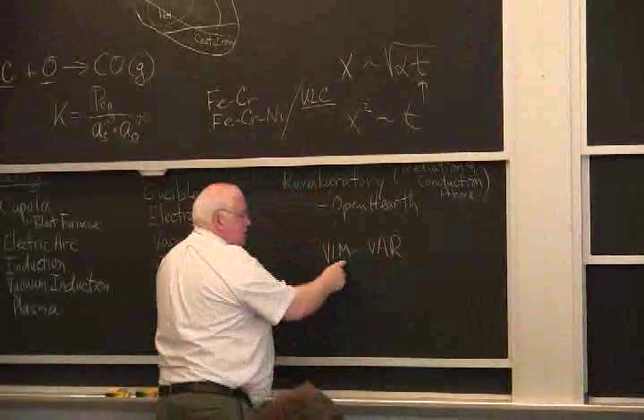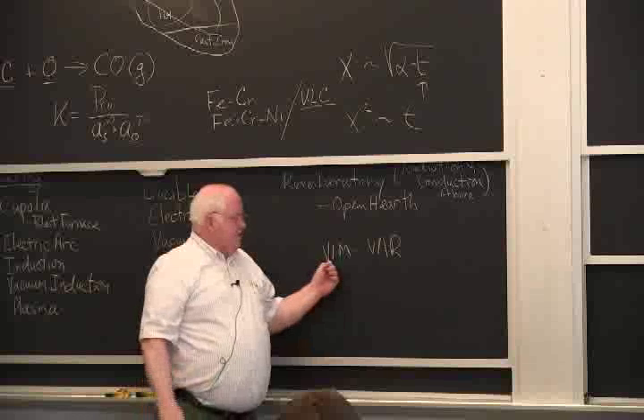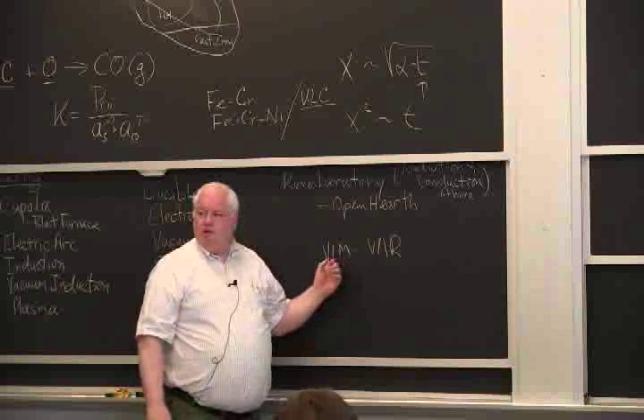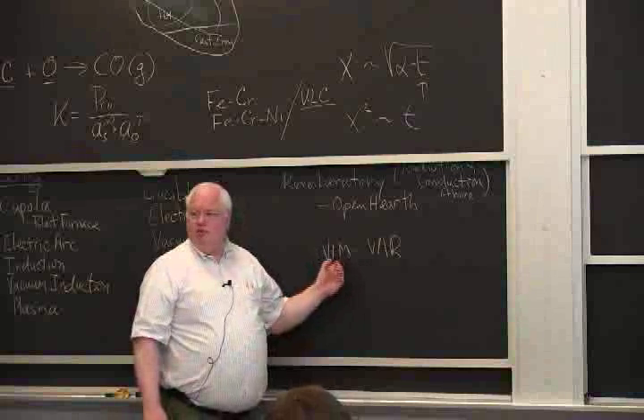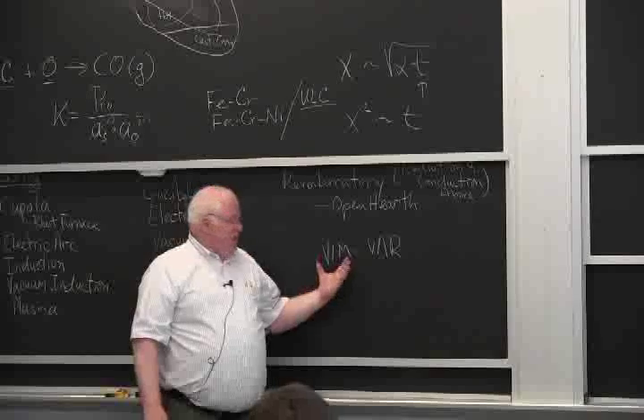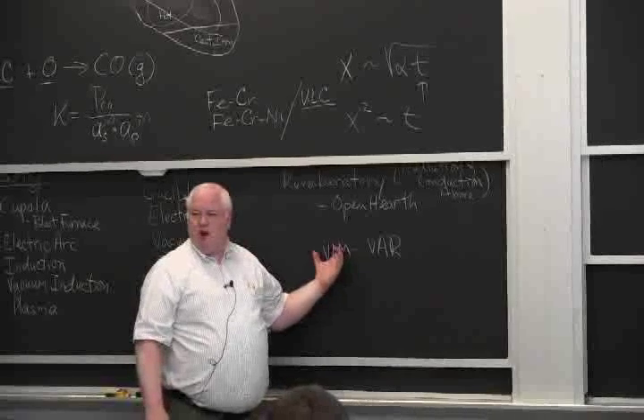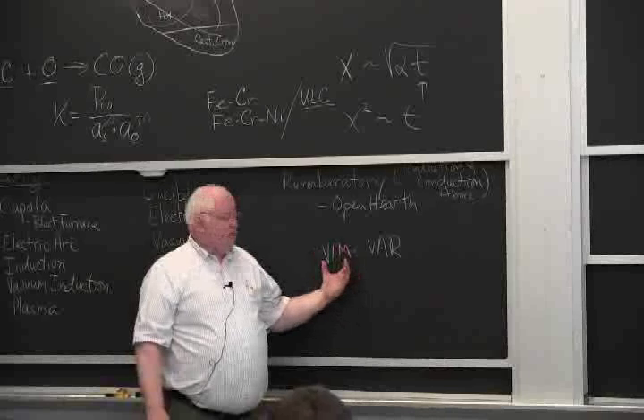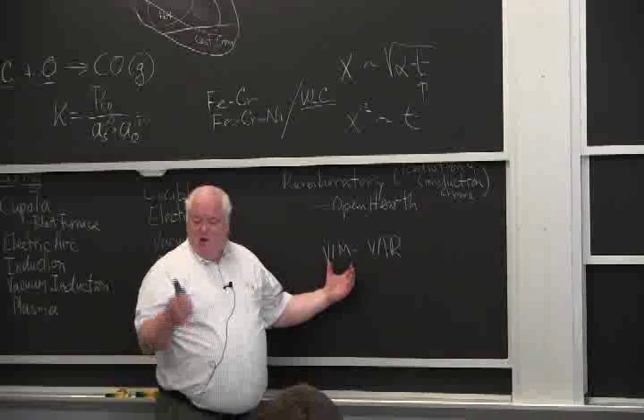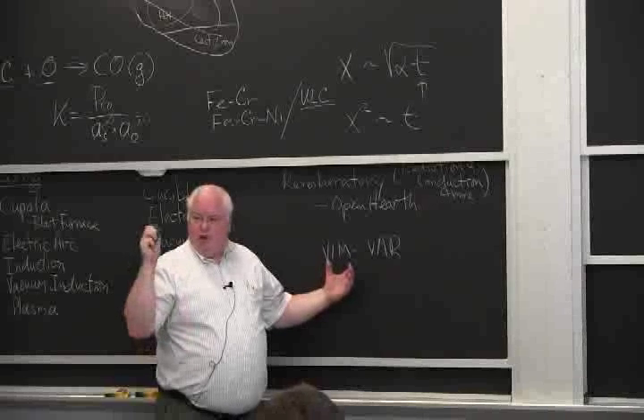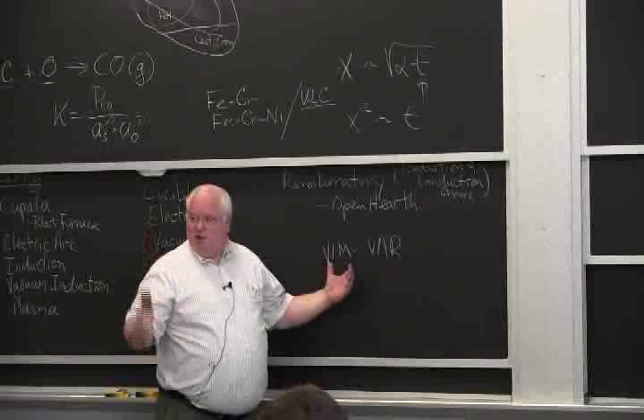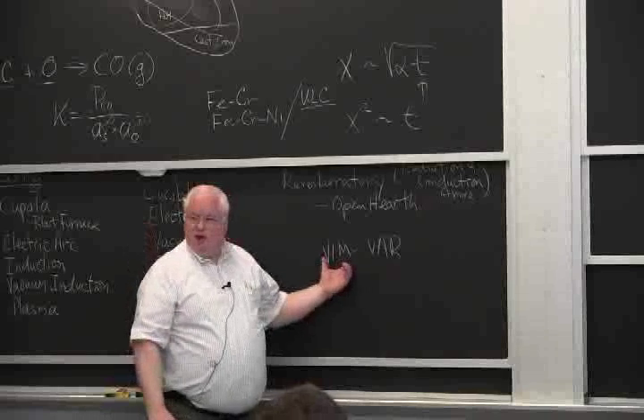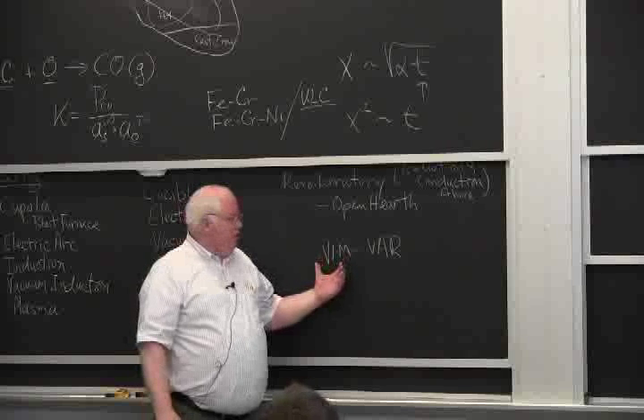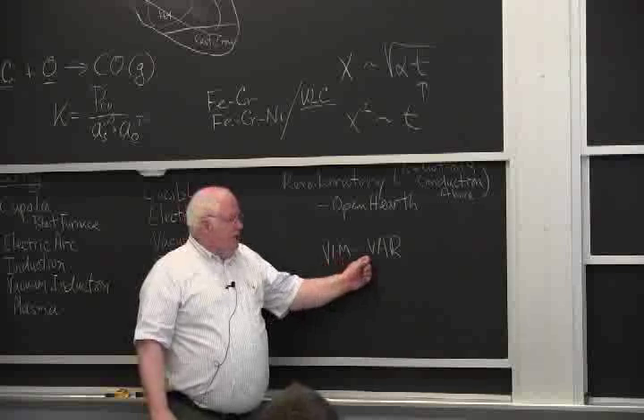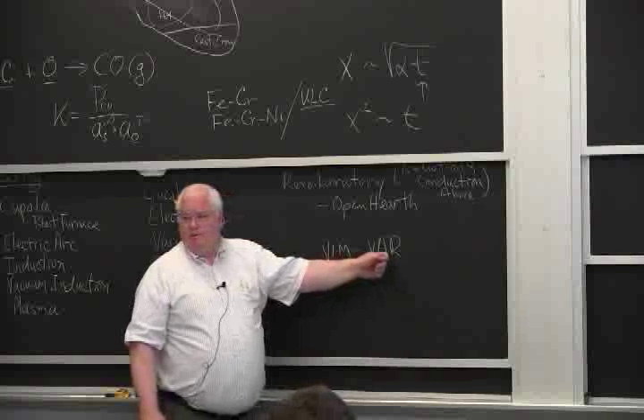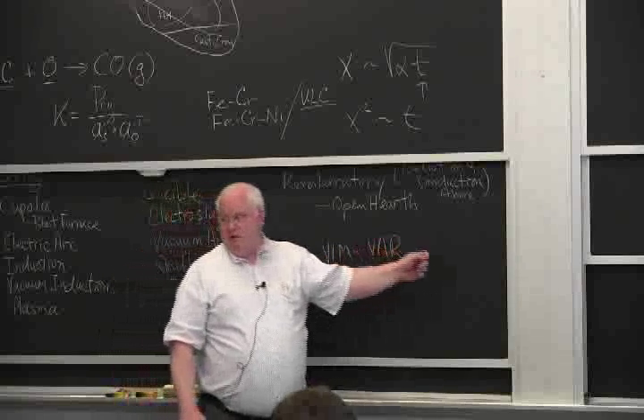Typically for a turbine blade, the vacuum induction melted, and typically for the best materials it has to be all virgin material. Virgin nickel, virgin chrome, virgin molybdenum, no scrap, because scrap will have impurities and oxides on the surface that'll get into your material. One of these turbine blades will go for about $6,000 when it's all done, each, okay? So you're not gonna skimp on the incoming materials. You're gonna do vacuum induction melting and vacuum arc remelting. And it might be double vacuum arc remelted, okay?